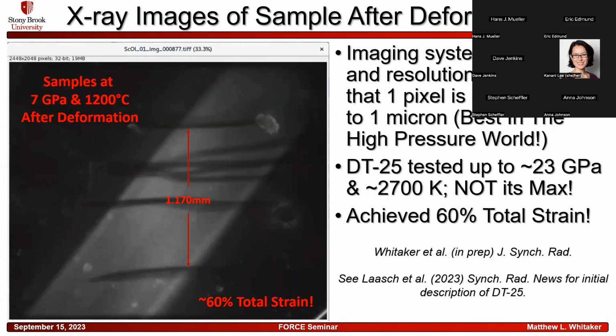And the DT25 currently has been tested up to about 23 GPa and 2700 Kelvin, but it's important to note that this is not the maximum conditions that it can achieve. And we've been able to achieve, as I said, 60% total strain. So this is a pretty exciting result that we have here.